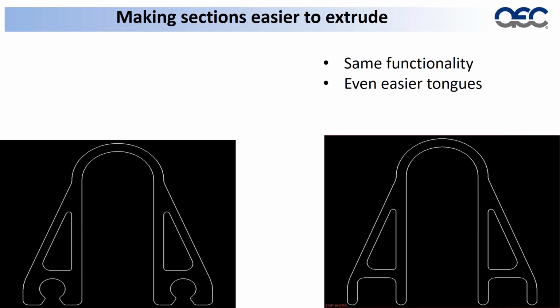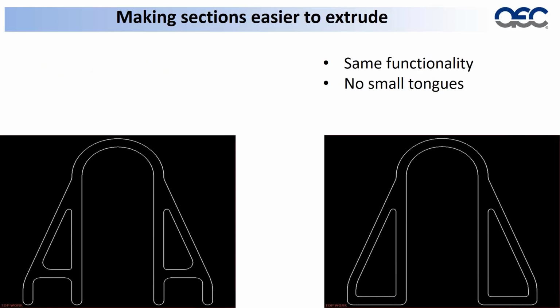Now, at the same time, we can look at the next shape, and we can see that in this particular case, if nothing was going to happen there, we can simply take a cut out of the extrusion and reduce the mass by adding a channel there and having 2 small legs that can sit on whatever the base piece is that's required. Again, easier tongues, less chance of breakage, metal thickness is uniform all the way around, and before we know it, we have extrusion consistency, which leads to customer delight.